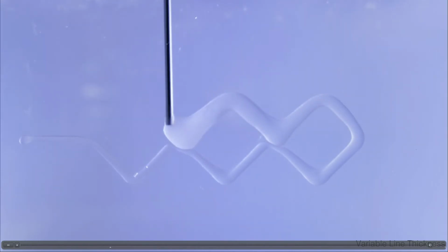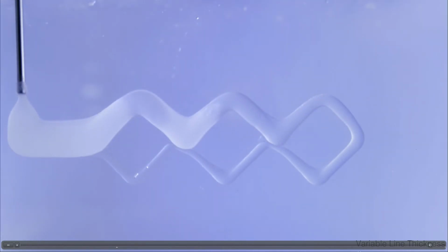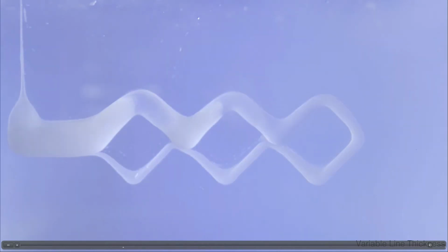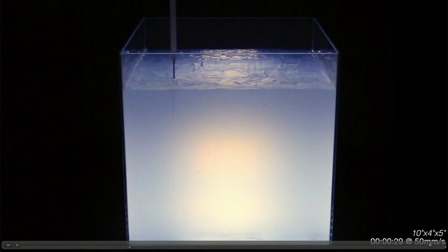And by printing into a gel, you eliminate gravity. So without gravity, you can print in 3D space, like calligraphy. So you're just drawing in 3D space as fast as the machine can go. And by changing the pressure of the extrusion, you change the thickness. So exactly like calligraphy. The material then cures underneath the gel, so you don't have to wait for it to cure. And you pull it out and just wash it with water.